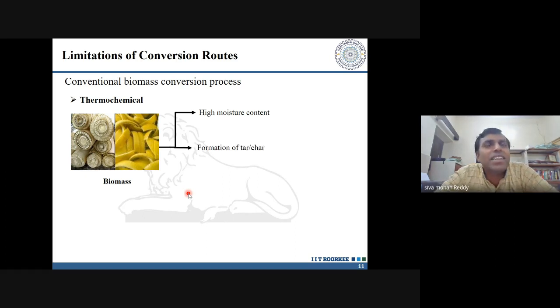Now the second key problem that we usually encounter whenever you are burning, or having a thermal treatment, is a lot of formation of tarry compounds. This tar is nothing but a non-condensable carbon paste, a thick slurry kind of thing. When mixed with char, it forms clinkers, and it becomes very difficult for us to handle in the gasification process. And the third one is that because of the above limitations, the gas yield is significantly reduced, right? So in these thermochemical processes, you need very sophisticated designs, or very high temperature, high pressure reactions, where you can enhance the gas yield significantly, right?